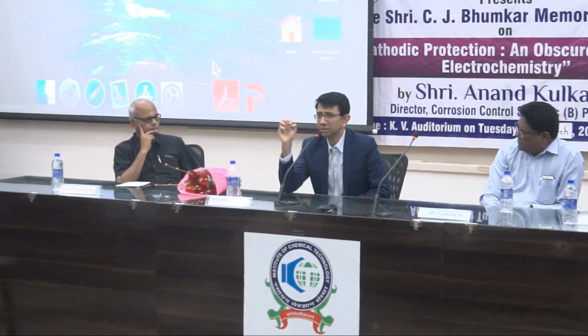Well, OCP now, when you already understand CP, it becomes more academic, doesn't it? Because OCP simply means the potential that a structure exhibits when it is not connected to an external load. The idea of the OCP is to understand the concept of corrosion and cathodic protection. So the idea is, if I have open circuit potentials of cathodes, which are say minus 500 millivolts on average, and I have open circuit potentials of the anodic sites, which are say minus 700, then the idea is to polarize all these cathodic sites so that I don't anymore have cathodes or anodes for that matter. So it is more academic. You're not anymore interested in OCP because you want to protect the pipe.